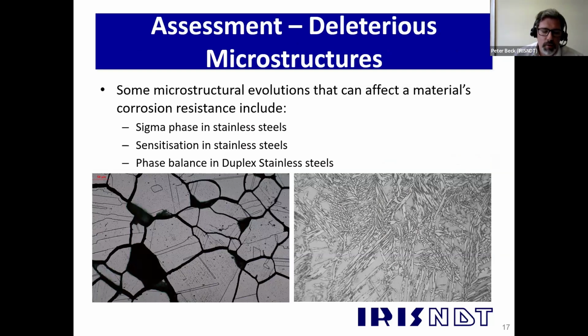Another thing that we can do is looking for deleterious microstructures. Typically with stainless steels, one consideration is sensitization. So we can actually etch the structure very heavily and see if we get this kind of ditched structure, as they call it. So that's the image on the left, showing a sensitized austenitic stainless steel.